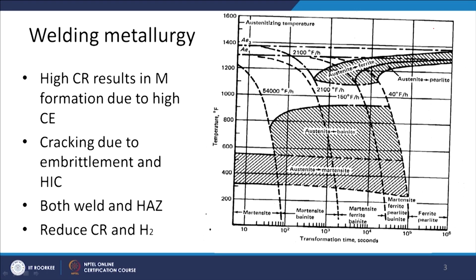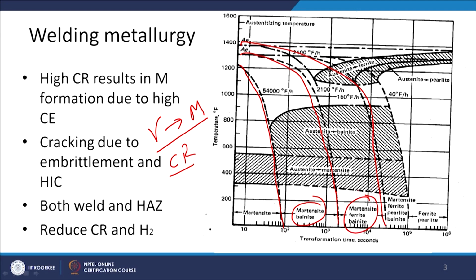As I have said, what different phases will be formed during the cooling of the austenite to the room temperature will depend upon the cooling rate being experienced. If the cooling rates are high, then we will be having the complete austenite to martensitic transformation. If it is somewhat lower, then we will be having martensite and bainite mixture. If further lower cooling rates using the higher preheat temperature is realized, then we will have ferrite, martensite and bainite. Further lower cooling rates will allow us to have martensite, ferrite, perlite, bainite in this typical 4340 grade steel. This is the continuous cooling diagram for 4340, which is indicating how the cooling rate can change the kind of phases which will be formed.